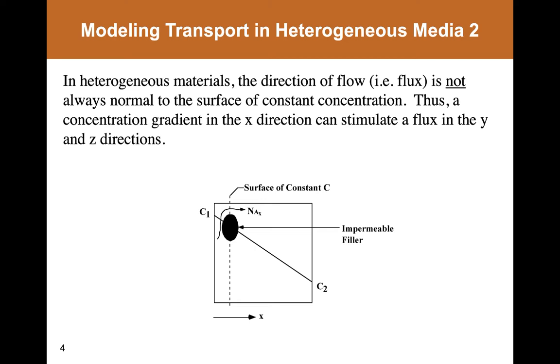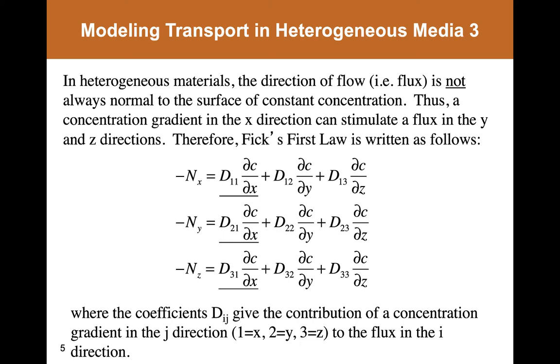And in these cases, the more general version of Fick's law is shown here, and you can immediately begin to appreciate the issue of trying to describe, in an analytical sense, transport according to the equations that are shown here. We have now 9 different diffusion coefficients. So if we look at the first expression for the flux in the x direction, there's a diffusion coefficient that is basically governing the relationship between the flux in the x direction and the concentration gradient in that direction. There's a different diffusion coefficient because perhaps the material heterogeneity looks different to the penetrant or presents a different resistance to mass transfer in the y direction and in the z direction. And likewise with the y and z components of the flux.